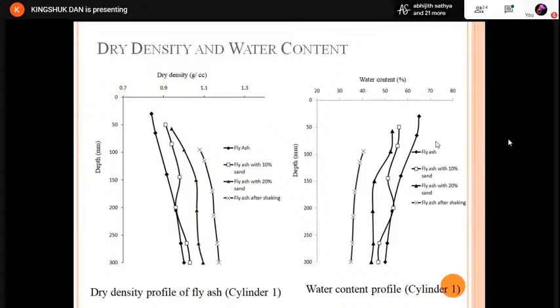Okay. Now this is dry density and water content behavior. From dry density behavior, we can see that with addition of sand, there is an increase of the dry density and a decrease of the water content. This is because when sand is mixed, the drainage length is reduced, and there will be a chance of lateral drainage. That is, water content is reduced, and when shaking is happening, the dry density is increased and water content is reduced. For cylinder 2 and cylinder 3, for the upper layer, this improvement of dry density is not so prominent. But for cylinder 1, we can see there is an appreciable increase of the dry density for the upper and lower layers also.